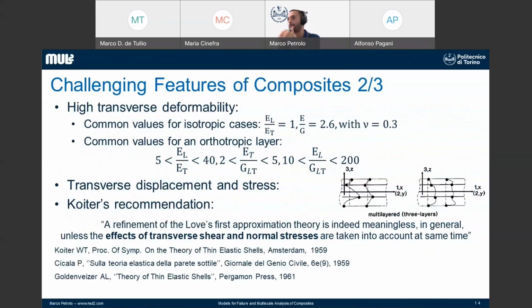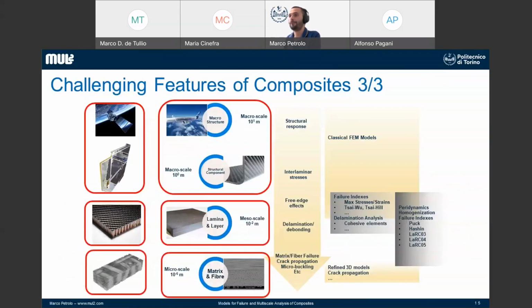This is just a few numbers to give you an idea of what we need for higher shear deformability as compared to metals. Here we have the ratio of Young moduli and shear moduli and the comparison with metals on top. Usually we have a number in the range of 3, and in the case of composites, we can easily have 100. This is one of the metrics we use to define shear deformability. This is a very simple case in which you can see how the shear deformability is way higher in composites, so you need to take it into account in your model.